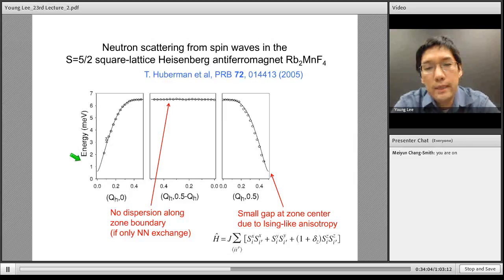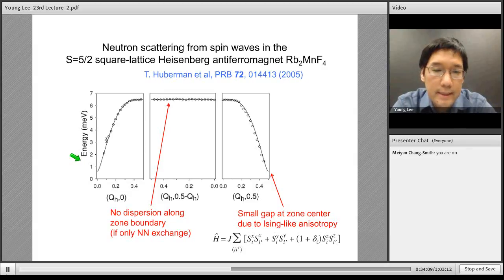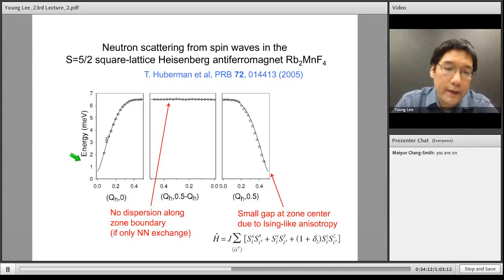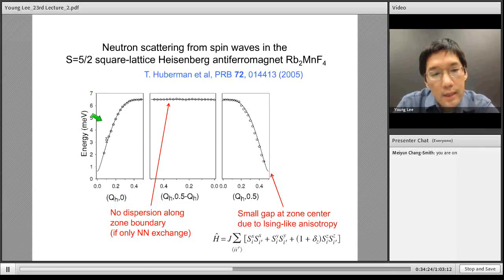If you now look along different high symmetry directions and you plot the position in energy at different wave vectors, you get the following dispersion plots. Going from a zone center to some zone boundary in the first panel, you see that it does look quite linear over some region before it flattens out. Let me jump over here. As well, it looks like there is some linear region. One thing I want to point out, though, is that it looks like this does not go to 0.